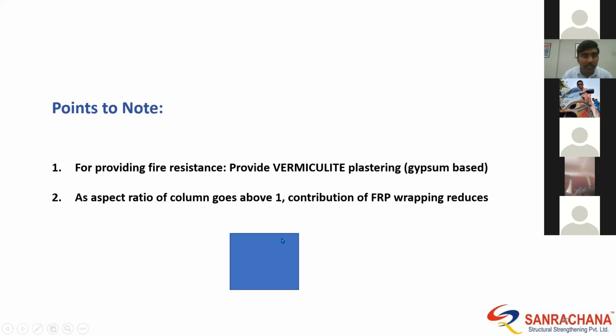Again, the aspect ratio of the column, as it increases beyond 1. What is aspect ratio? Breadth to width. So if it becomes more rectangular, then the FRP's compressive strength capacity reduces. As in, when you try to increase a column's strength by using FRP wrapping along the hoop direction, and if the column's aspect ratio is very rectangular, then its contribution to compressive strength is reduced. That is what I want to convey. However, the shear strength does not reduce, because that happens not through a contact critical mechanism, it happens through a bond critical mechanism.